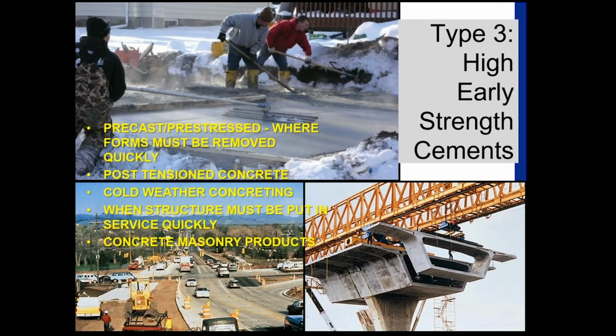Type 3, high early strength cements, absolutely something that we're starting to see now put into application this time of year with cold weather concrete. Also a lot of precast prestress where forms need to be removed quickly. Post-tension concrete could be type 3 use. Any kind of pavement where that's a fast track or where that's a high traffic area that needs to be put back into service quickly, or a lot of times we'll see even still some concrete masonry products, again, especially when that has to be turned around quick or we're concerned with chippage on corners or something like that on the fine detail work, that might be a place for type 3.